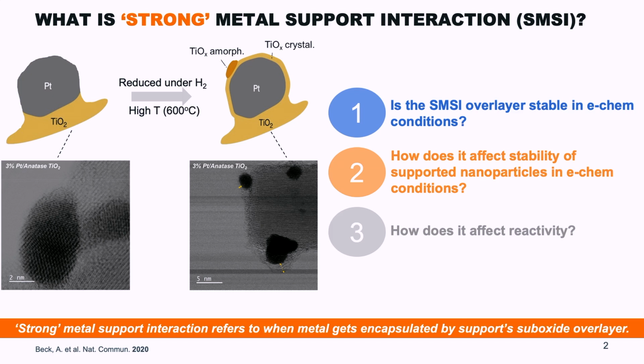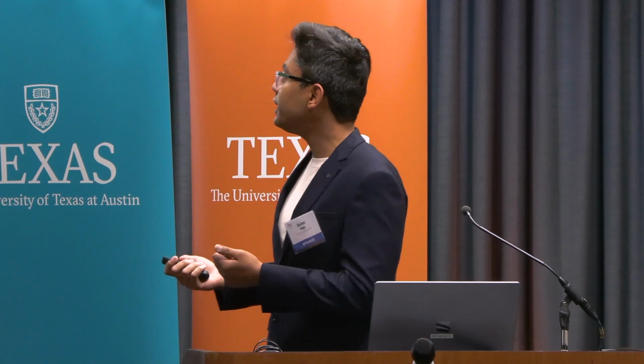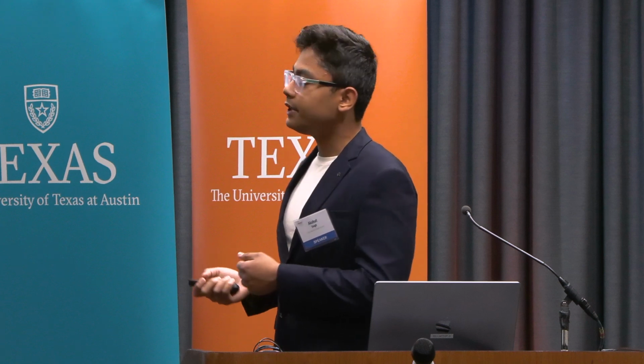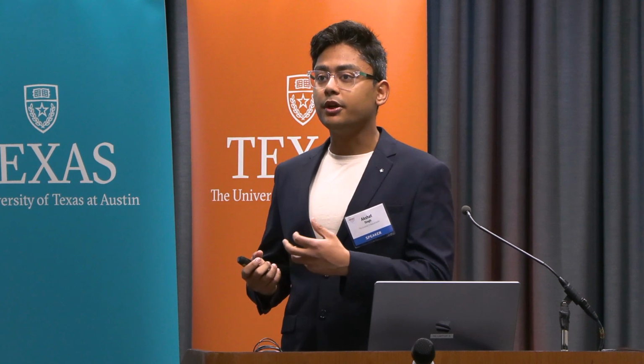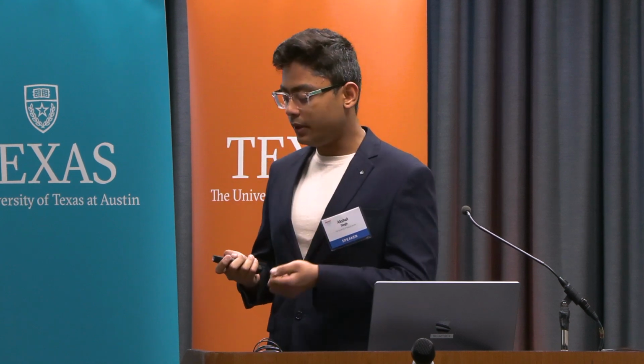Using this model system of platinum supported on anatase TiO2, we reduced it at high temperature, 600 degrees Celsius, and saw encapsulation of the platinum nanoparticles with a very thin overlayer of TiO2. And so through my presentation, I'd like to answer 3 specific questions. Firstly, is this SMSI overlayer even stable in electrochemical conditions for it to be of any use? Secondly, how does it affect the stability of the supported platinum nanoparticles under applied voltage and pH? And thirdly, how does it affect reactivity?